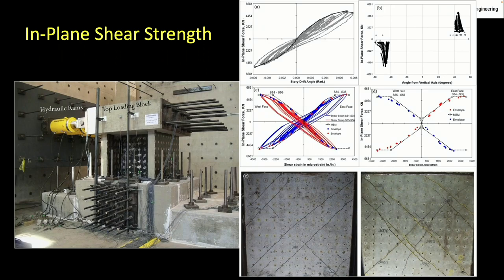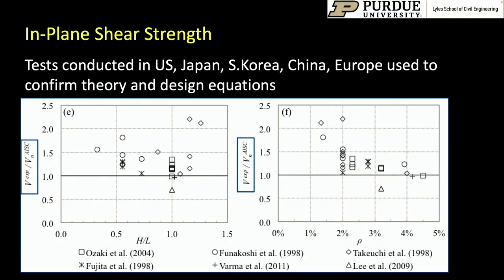This equation was verified through large-scale testing that was done in our laboratory. Here, I'm showing you a comparison of the trilinear curve with the backbone of the experimental data that we obtained from the in-plane shear behavior of this stocky or short squat shear wall. Besides that, after the testing had been completed, we removed the steel plates in order to examine that those 45-degree cracks were indeed forming, and we also identified the principal strains that we were measuring on the steel plates to be anchored right around that 45-degree point in both directions.